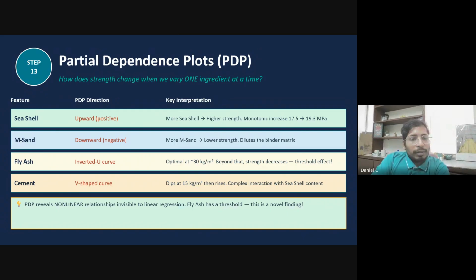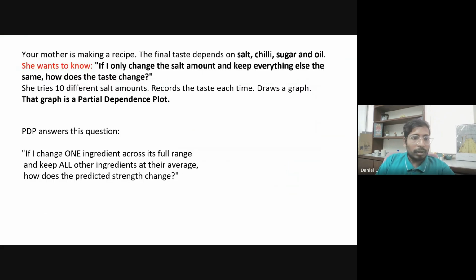Now for seashell, if you see the graph, it's going towards up, right? Positive, which means more seashell you are adding, higher the strength, right? Because if you see the data sets, compressive strength starting from 17.5 till 19.3, it is getting increased when we are adding more seashells. Then in M sand, you can see in between you will find a negative, which means the mixture M sand at certain ratio, it reduces the strength. Then fly ash, you can see the inverted U, and cement you can find a short V curve. So you can see one by one. I think this results you could have got.